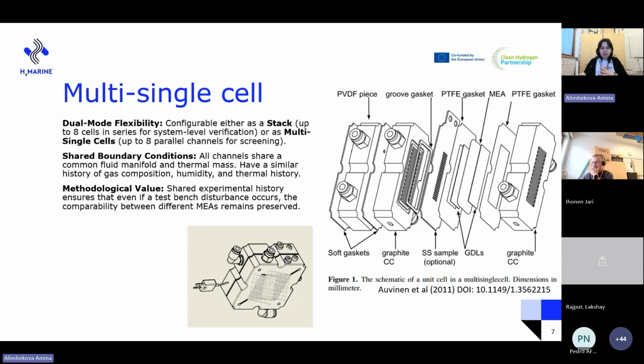Or you can test inside a short stack. The issue with the short stack is that the cells are dependent on one another. All of them are under the same conditions, the same kind of forces are on the cells, and the failure in one cell can result in skewed flows or current distribution in other cells. This is particularly the case under hydrogen-air conditions.